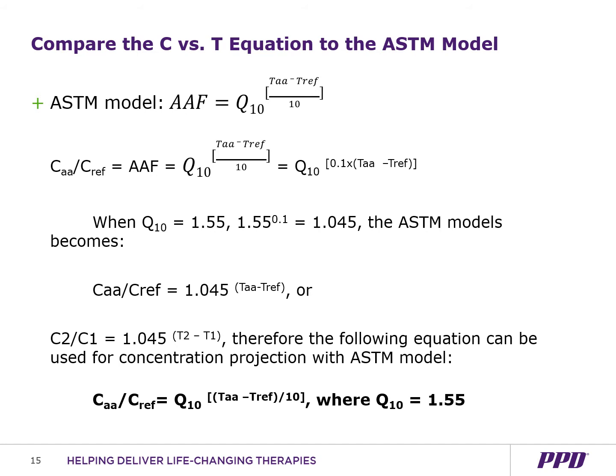And this allows us to say that we could use the ASTM model with a Q10 value of 1.55 for a concentration projection of BHT extracted in the same material with the same solvent. This suggests that the ASTM model is appropriate for calculating and predicting extractable and leachable amounts at one temperature from amounts at another temperature when a suitable Q10 value is used.